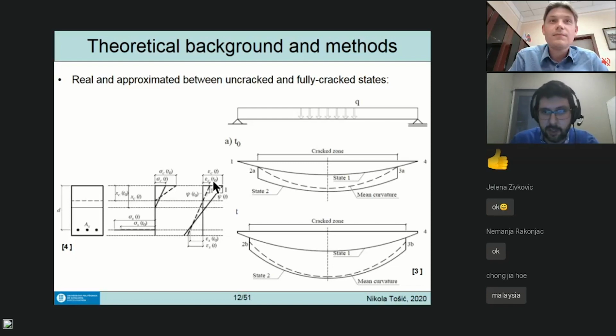Over time, this epsilon c - we'll see a relationship later - has the initial strain, which is what we have here, but now it's increased for creep and increased for shrinkage, going all the way up to here. Now our strain line is this. The curvature, of course, is the sum of these two lines divided by the strain in concrete and in reinforcement, divided by the effective depth.